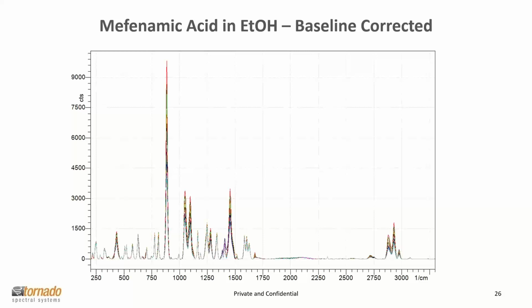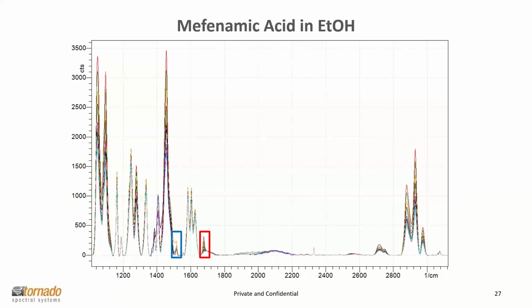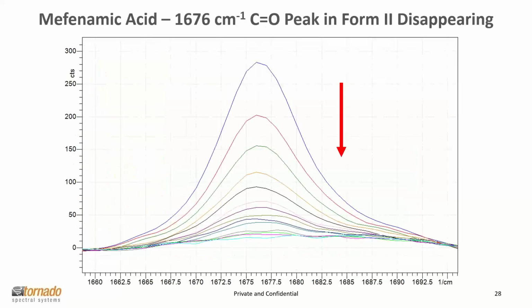And you can see that there are several places where the spectra are changing. And anytime you see changes, those can be useful in interpreting what's happening. Here's a little bit closer look at this, and I'll call your attention to two particular areas of the spectrum that turned out to be interesting. One was the same region that Thomas showed you earlier, which is the carbonyl band at 1676. And that band represented form 2, and that band disappeared. So form 1 had no such band present in its spectrum.